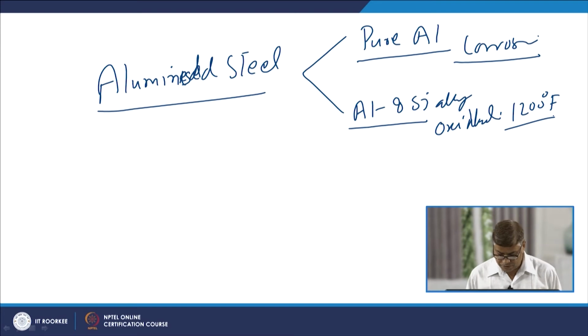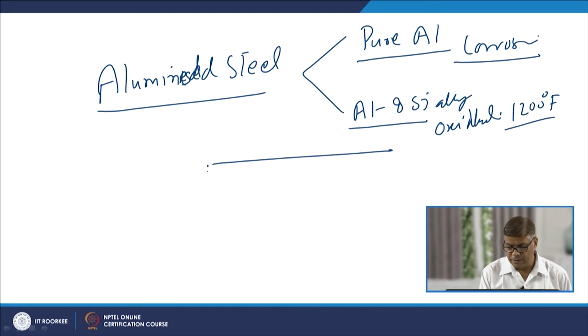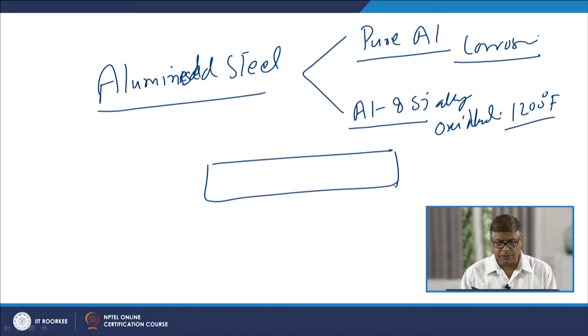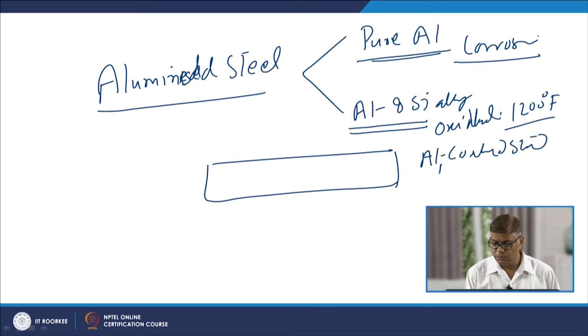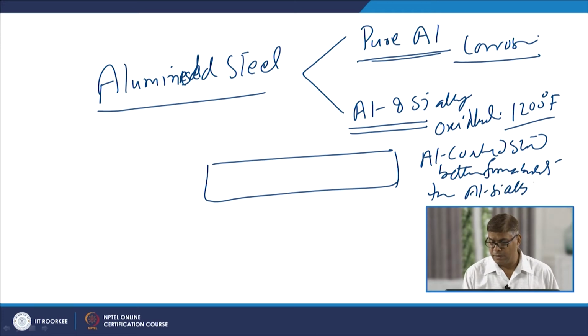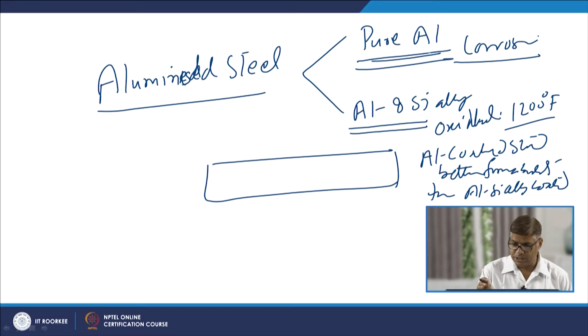So, the high temperature oxidation resistance is improved, but if we compare the weld joints of the steel sheets coated with pure aluminum and the aluminum silicon alloy, then the aluminum coated steels show better formability than the aluminum silicon alloy coated steels. So, this is one comparison as far as the pure aluminum and aluminum silicon alloy coated steel is concerned.